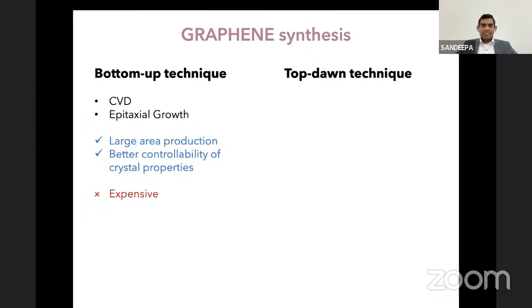What are the advantages of CVD graphene? Actually, it allows large area production. We can synthesize graphene in areas of a few feet, even, if we need it, and it gives better controllability of the crystal properties. We control it with the base catalyst materials. But this technique is quite expensive. We need to process at very high temperature, like 1000 degrees, and we need to maintain an extremely clean atmosphere as well.